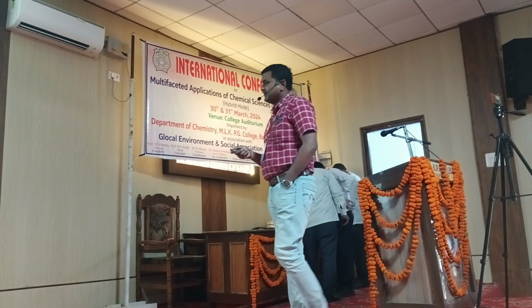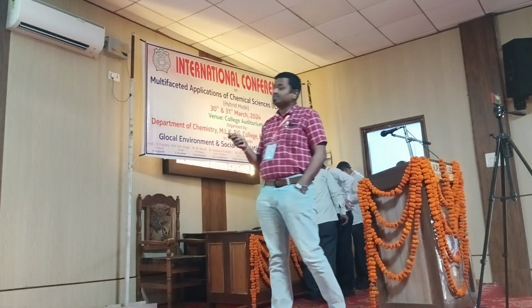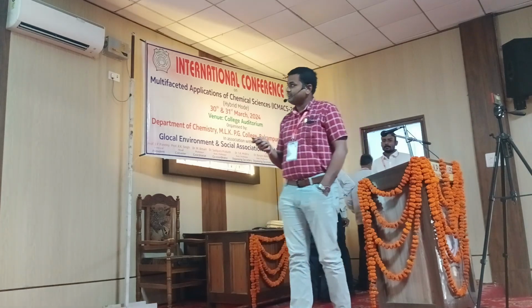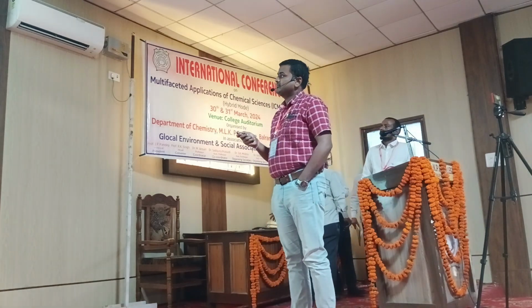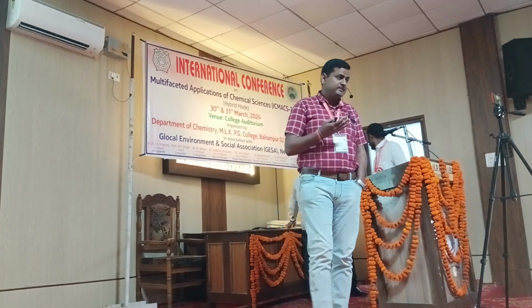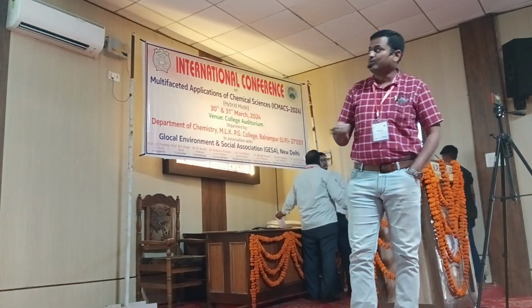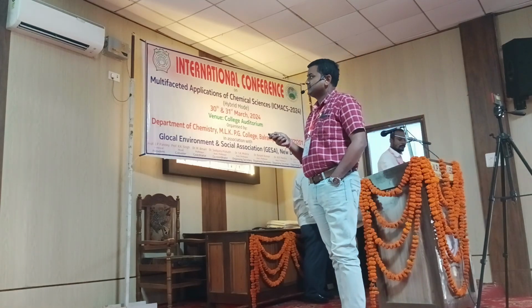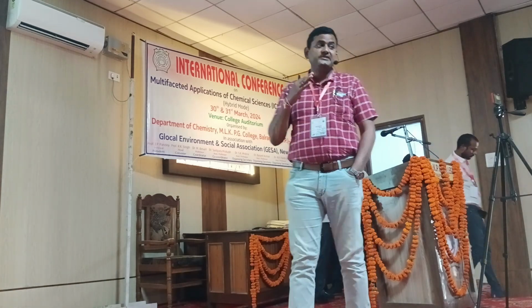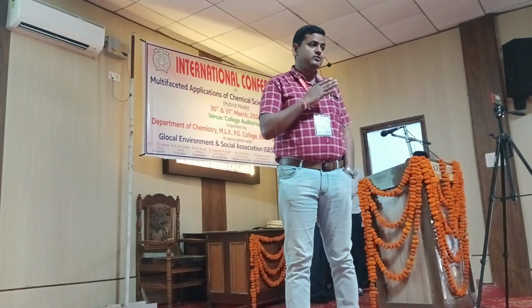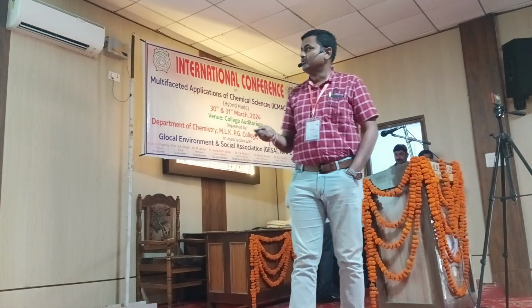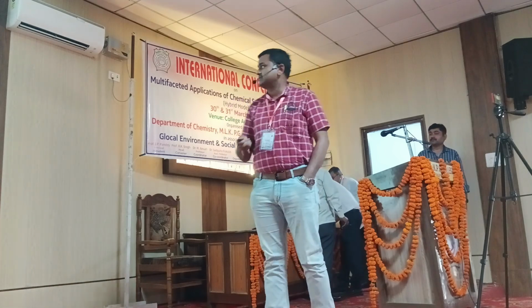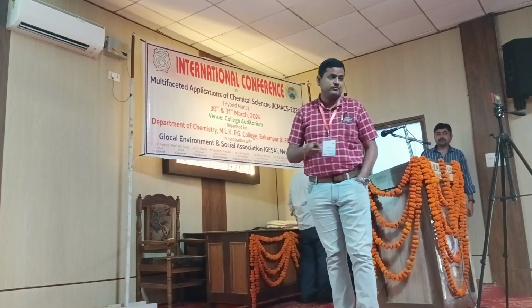So we have prepared white light emitting graphene quantum dots from coal soot, and we have filed an Indian patent for that. In the literature, most of the reported examples achieved white light emission by mixing red, green, and blue, which, as I told you previously, are complementary colors. We prepared white light emitting graphene quantum dots from coal soot for the first time from a single source and single material. We did not use red, green, and blue for mixing, and the developed process aids in the value addition and full utilization of coal soot for the production of white light emitting material.